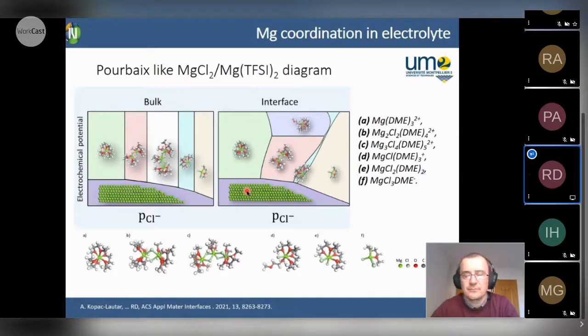But as it is already known from the literature, especially when you are working in magnesium chloride solution, our typical electrolyte is a mixture of magnesium chloride and magnesium TFSI. When you're working with that solution, there are many different species between magnesium TFSI molecules, chloride molecules, magnesium chloride and DME molecules.